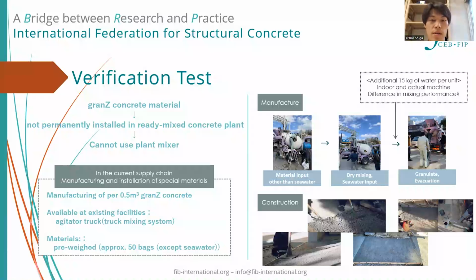Mixing performance of the base concrete after mixing was very different due to the difference in mixing performance between the laboratory mix and the agitator truck. So 15 kg of unit water was added. Thereafter, granulation was done and it was cast. The casting was completed using simple methods such as tamper and roller without the use of specific machinery, confirming the good quality of the construction.